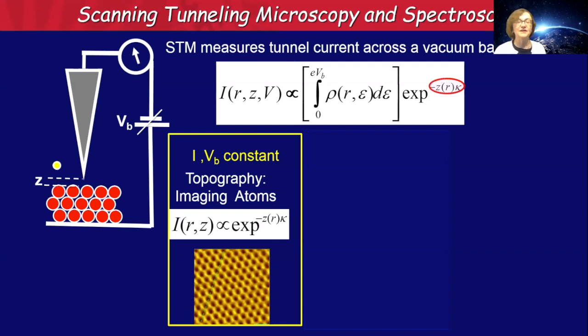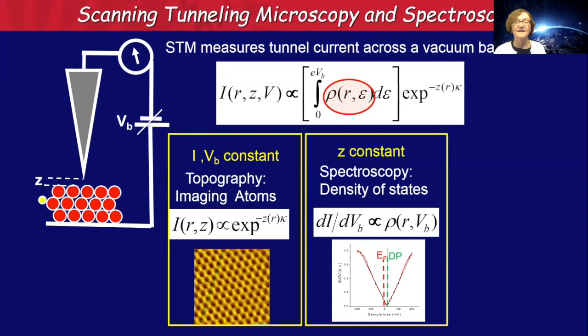In one, we keep the current constant and the bias constant, and we raster the sample and adjust the height of the tip so that the current is constant. That gives us an atomically resolved image of the atoms that sit in our substrate. Another mode of operation is one where you're looking at the density of states, and for that you just take the derivative of your current with respect to bias, and that gives you the density of states. This is an actual measurement of the density of states of a monolayer graphene, and you see it's linear in energy on the horizontal axis. So the density of states is linear in energy.